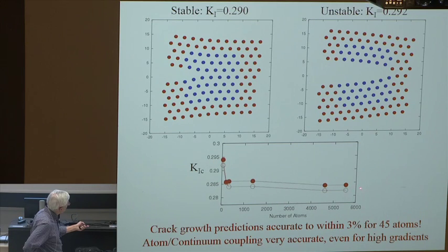And actually right about here. This is to grow the crack forward. This is actually lattice trapping. If I try to grow the crack forward, I load, it moves forward at a certain stress. It starts to close at a slightly lower stress because there's a slight atomistic effect called lattice trapping that gives a little bit of asymmetry. And so this is the Griffith point, but I could come all the way down here.